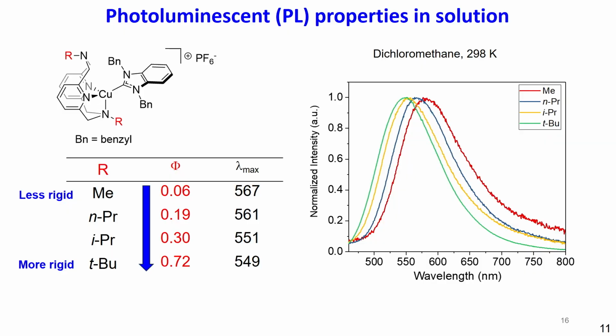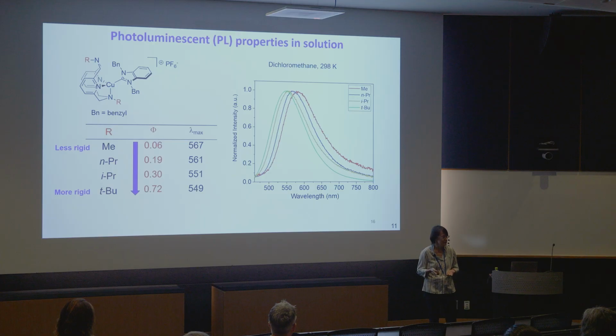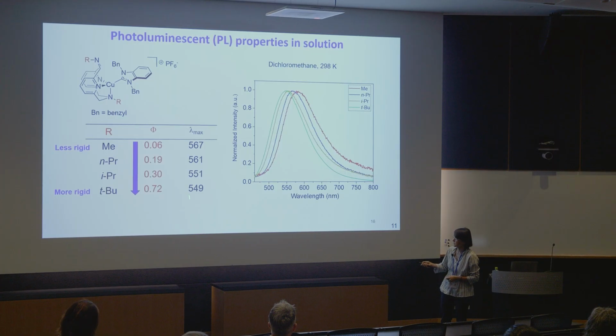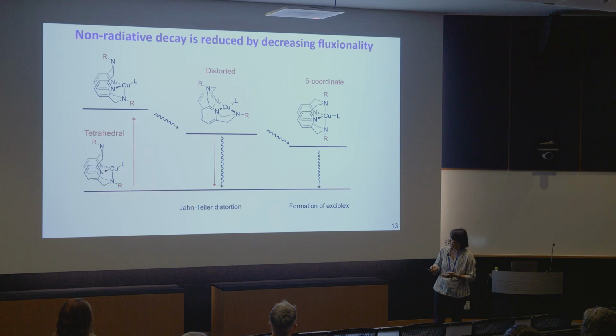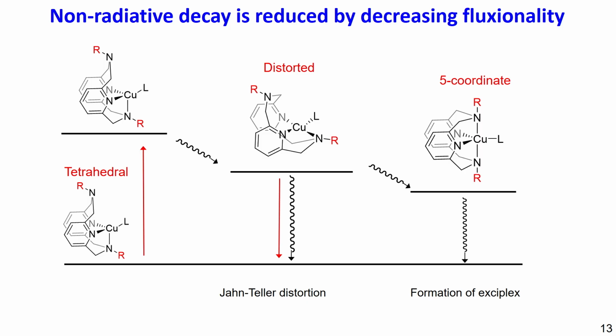But not only that, their photoluminescence was dependent on how rigid or fluxional they are. So by using different structures and different substituents, we can control how fast this exchange is, how quickly this nitrogen tail wiggles up and down. And we noticed that when the system is more rigid, then we obtain brighter emitting complexes, so photoluminescence quantum yield is increased. And when systems are more fluxional and dynamic and exchanges fast, then photoluminescence quantum yield goes down. So then, of course, this can be explained typically in literature regarding copper complexes through the suppression of the non-radiative decay, which typically involves this kind of dynamic behavior and structural distortions, for example, through Jahn-Teller distortion or through coordination of an extra ligand, and we just have this extra nitrogen tail sitting just around our metal. So this probably is the reason for this effect.